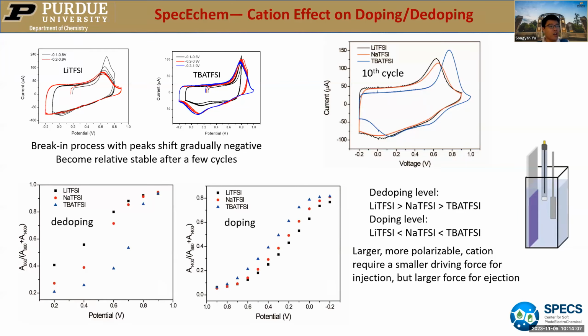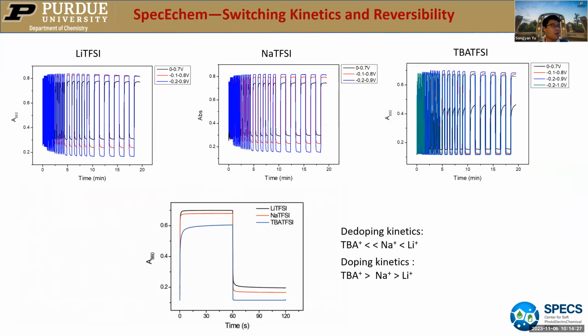So generally, a larger, more polarizable cation requires less driving force for injection, but a larger force for ejection. So that's why for the de-doping process, the TBA TFSI requires a larger driving force. So for different electrolytes, they have different doping or de-doping levels. And also compare their switching kinetics. As long as we work in a safe potential range, their switching reversibility is quite good.